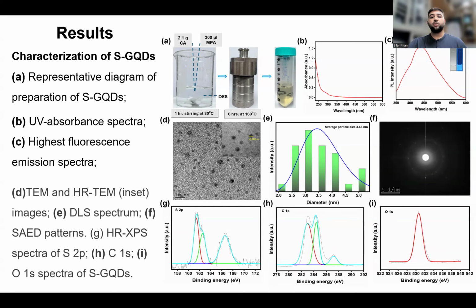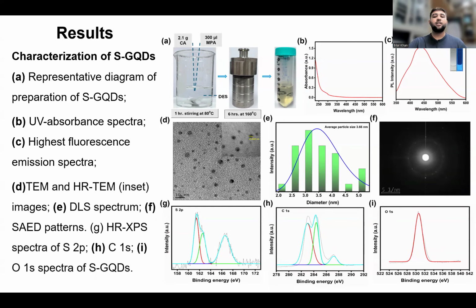And then through TEM and HRTEM, we checked their structural morphology. And from DLS, we see that the average size of graphene quantum dots was less than 10 nanometer, around 3 to 5 nanometer. And the SAED patterns of the specific area show the polycrystallinity of our graphene quantum dots.